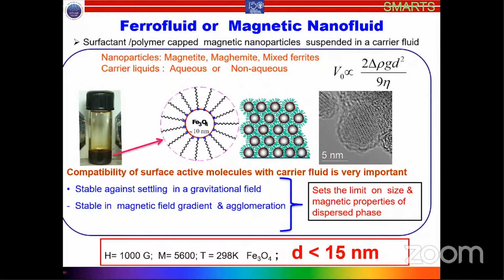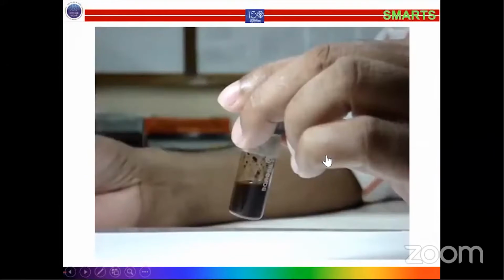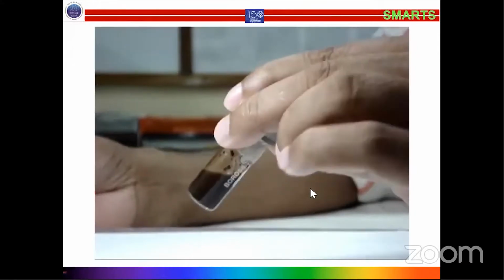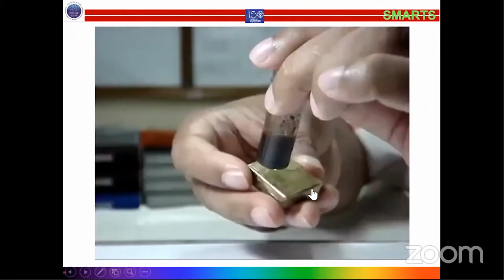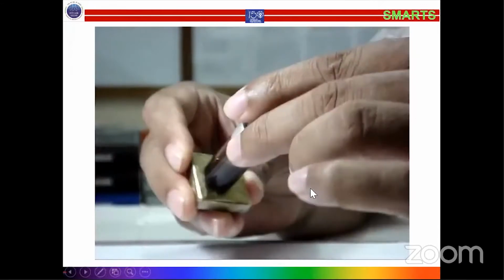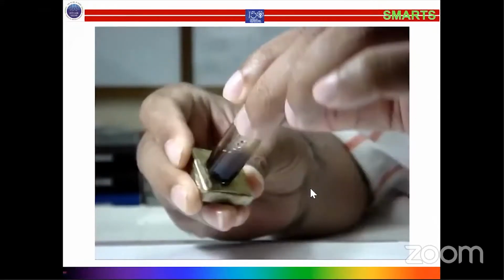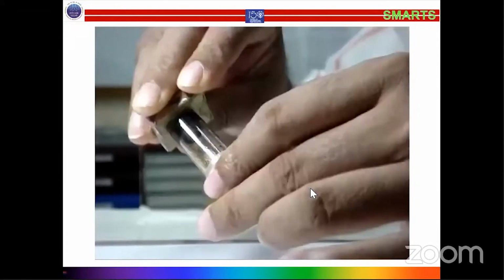So to show you an example of the importance of surface capping in stabilization of this kind of colloidal system, I have another movie here. In the first movie, you saw particles capped with surfactant molecules, and the particle size is around 10 nanometers. If it is not properly functionalized, what happens to this fluid? That is what you see in this movie. The size of the particle is exactly the same. The particles are the same, that is the iron oxide. The only difference is that the capping is not proper. The functionalization is not proper. Now you see the difference.